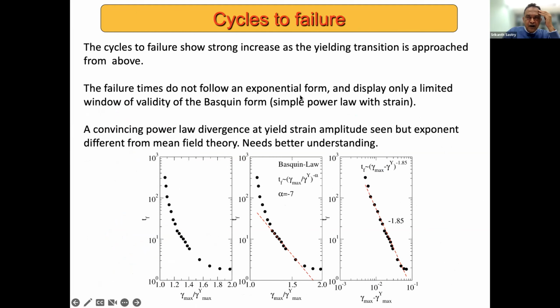So one can now look at the failure time as a function of the amplitude of shear deformation, and ask, does this obey any of the forms that people have discussed earlier? One such form is the exponential form, and this was in fact even seen in the mean field theory, but we don't find that to be a valid description, nor do we find what's called the Basquin form, which is a simple power law with respect to the strain amplitude. That's valid in some limited range of strains, but as I get close to the fatigue limit or the yielding point, I have a stronger divergence. What seems to be a good description is a power law, but with an exponent that's considerably larger than what we found in the mean field theory.